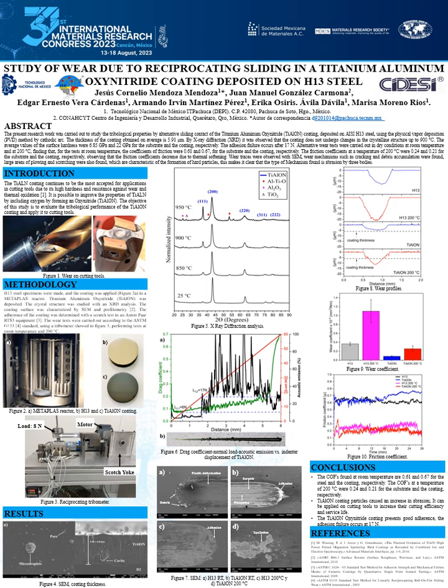Figure 9 shows the wear coefficients. The titanium aluminum oxynitride coating presents a high resistance to wear, which is why it has the lowest wear coefficient. This is attributed to the high adherence of the coating with the H13 steel.